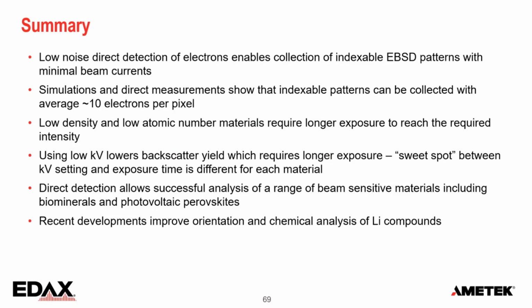And now just to summarize this, when you have a low noise direct detection, you can get indexable, nice quality EBSD patterns with minimal beam currents. In many cases, you only need about 10 electrons per pixel of the diffracted signal. It depends a little bit on the atomic number and the background how much you actually need, but that's more or less the limit. If you go to low density materials, light materials, you need a bit longer. And you may have to find your sweet spot between kV, the backscatter yield, and the sensitivity to damage of a material, to find where you are getting the best results.